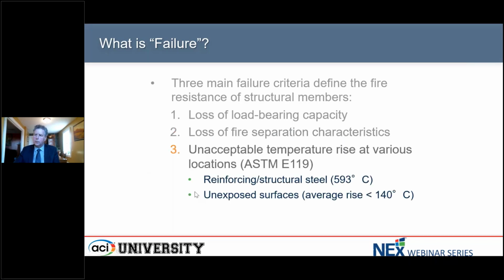And the third one, in a way it's really related to the first two, is about unacceptable temperature increases at certain locations. So for the unexposed surface, that's an average increase of 140 degrees centigrade. And once again, that's a little under 300 degrees Fahrenheit in terms of the increase in that unexposed surface.